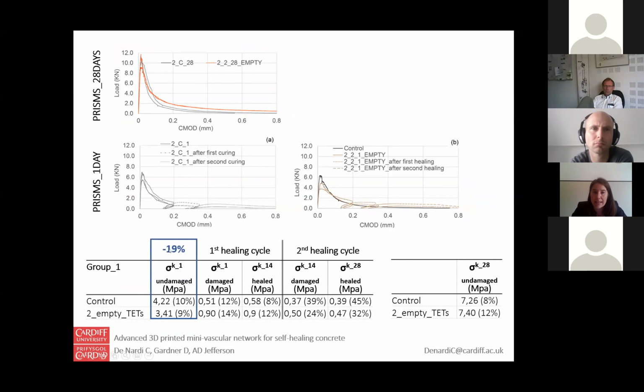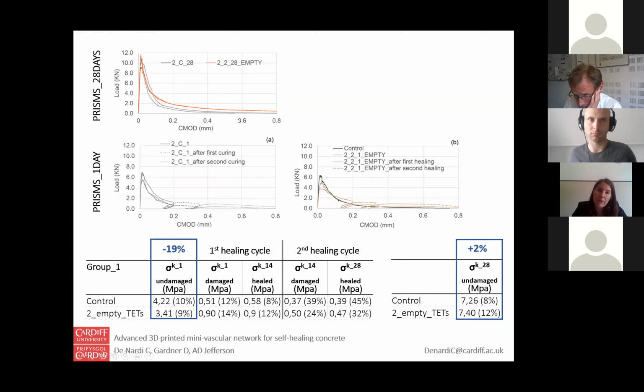The presence of TETs marginally reduces the flexural strength of samples tested after 1 day. But on the contrary, on samples cured until 28 days, the flexural strength is almost similar. It's even a little bit more. And moreover, if you have a look at the load-CMOD graph here, the presence of TETs seems to bridge the cracks when the majority of the concrete ligaments are already lost, and it acts as a kind of reinforcement.